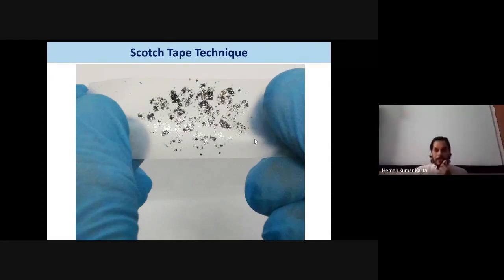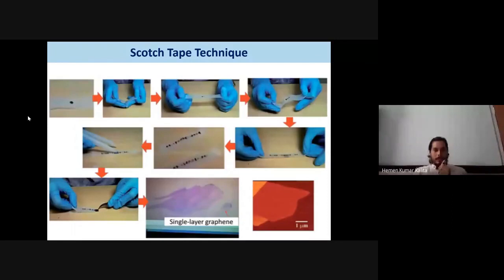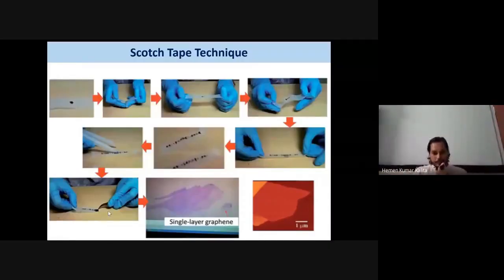The method looks something like this. In slide number 12, the image is a little bit blurry, but still we can see this is a Scotch tape. On the Scotch tape, we put a graphite flake, and then we stick the Scotch tape together so that it gets peeled off, and this process is repeated. There will be a series of peelings done on the Scotch tape, and we continue until we think it is peeled so much that we get a very thin layer. After that we transfer that peeled graphite onto a substrate, maybe silicon or silicon dioxide, and then we observe under a microscope.